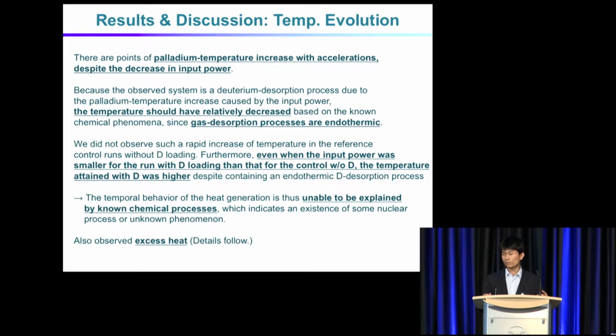The main feature was the temperature. We have some points of drastic increase in temperature, despite the decrease in input power, so it may indicate something. Also importantly, the observed system is a deuterium desorption process, because the temperature of the sample is rising, and basically desorption of deuterium happens, but the palladium temperature increases. Basically the gas desorption processes are endothermic, so the temperature should decrease because of the desorption, but our experiment says the temperature is increasing.